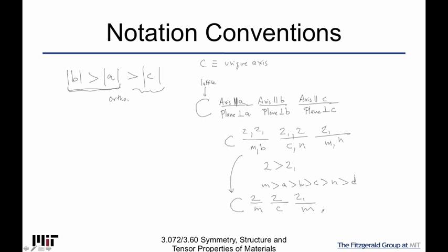And it shows you that the notation is created so that if you put those major elements in, the other ones should follow. So for example, in this case here, I didn't put a 2_1 in there, but if I put in a 2 with a perpendicular mirror plane in this direction, and then I put a 2 in with a glide plane on C, and then I put a 2_1 with a mirror plane perpendicular to it here, then all the other things will be generated anyway, and I don't need to put in more information. And so that's the kind of concept behind the international notation.